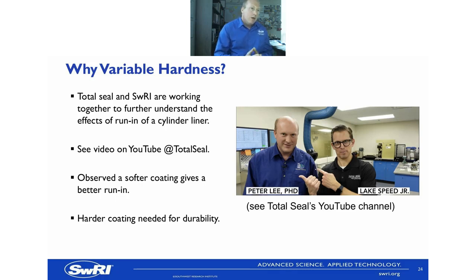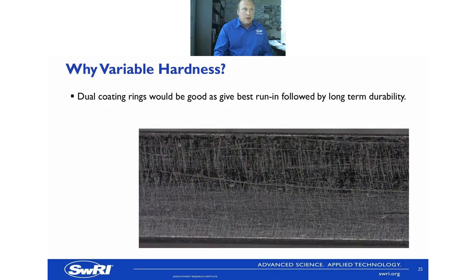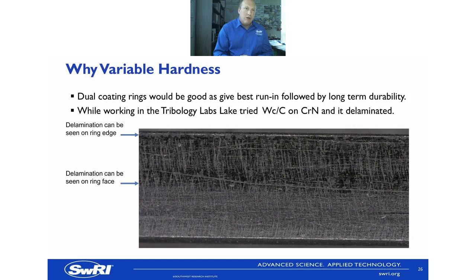Now, what we did observe was that a softer coating gives a better run-in, but that isn't any good, because that coating is eventually just going to disappear because it's soft. And then what you need under that is a hard coating. So if you do that, and here's a picture of a piston ring, you're at this point saying you need a dual coating. Now, dual coatings unfortunately don't work that well.